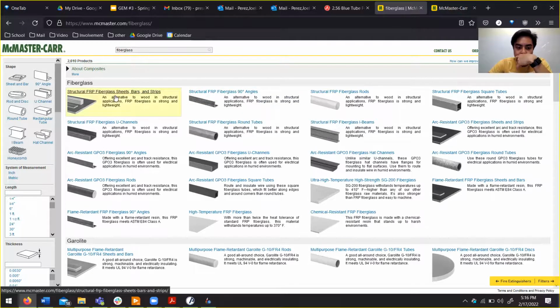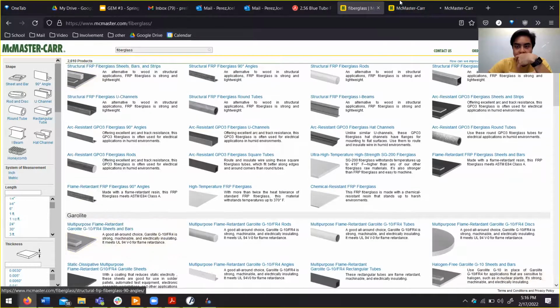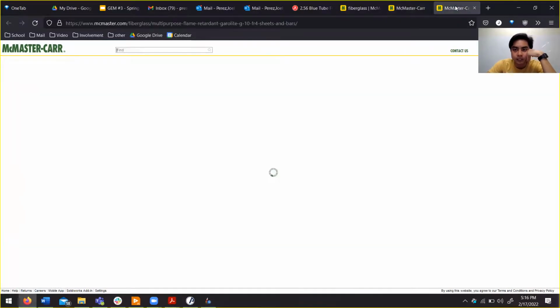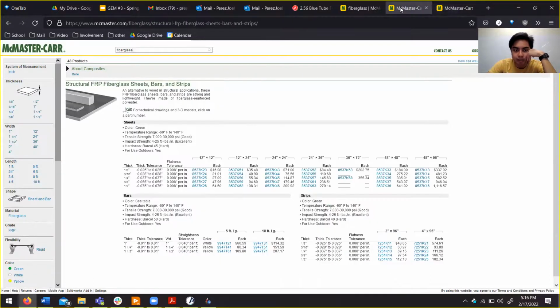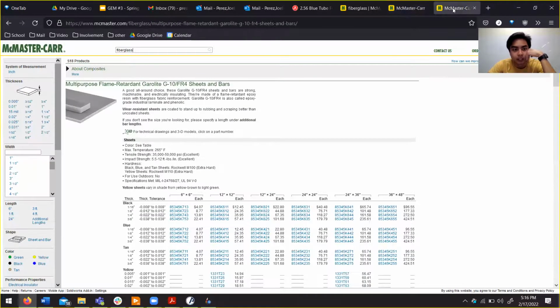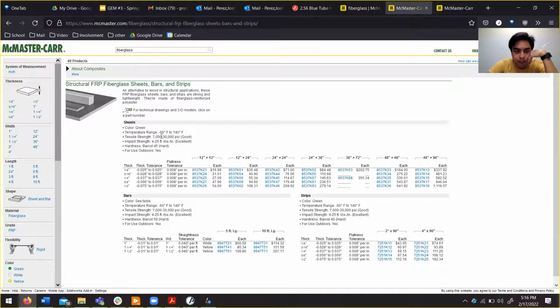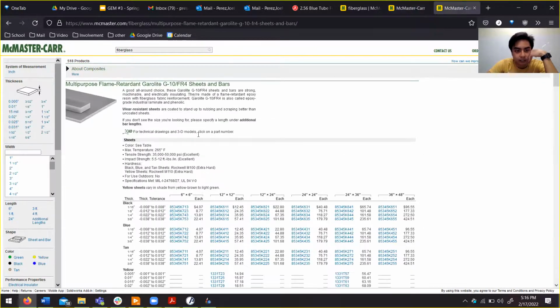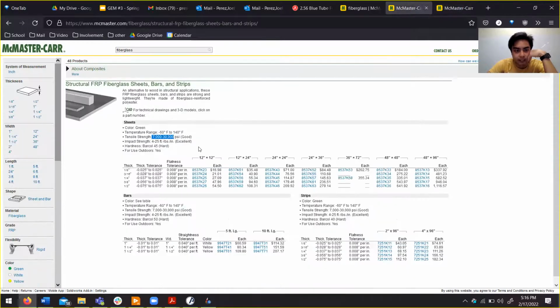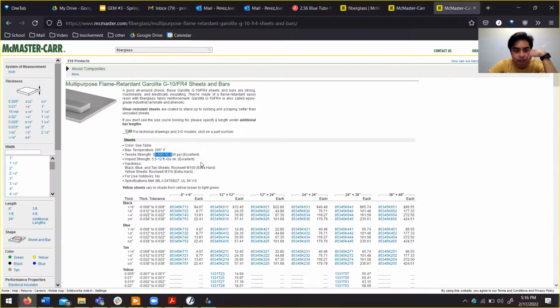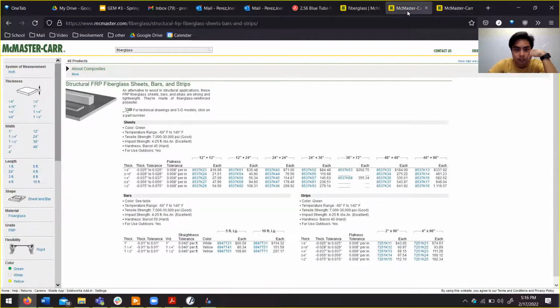We have structural FRP fiberglass, and then we have Garolite G10. While there's nothing wrong inherently with either one, one of them is significantly better. So G10 fiberglass, if you look at it here, has a tensile strength of 35 to 50,000 PSI, impact strength of 5.5 to 12. We compare that to structural FRP, tensile strength 7 to 30,000, compare that to 35 to 50, right? Impact strength 4 to 25 compared to 5.5 to 12.